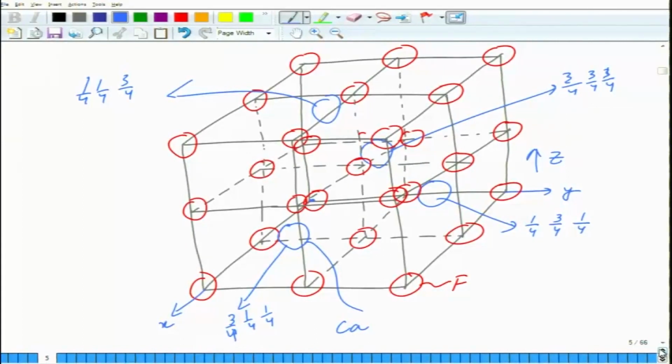So, now this calcium fluoride structure is followed by a variety of materials. There are a lot of fluorides which follow this structure. So, CaF2, but you also have ZrO2, UO2 and various other oxides follow this structure, okay. So, these are all ionically bonded solids. Now, another compound in this series is called antifluorite.